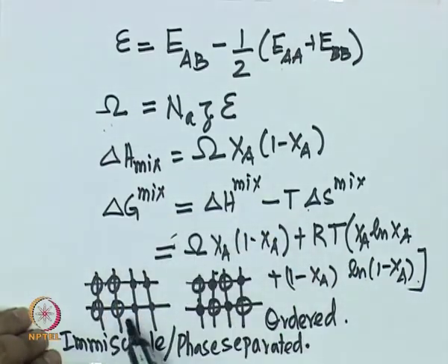the sign of omega decides whether the system is going to phase separate or the system is going to order. The models that we are going to talk about in this course, which are known as phase field models, are basically models meant to study this kind of phase separation by a specific mechanism known as spinodal decomposition, and ordering. Basically, all phase field models can be thought of as models built from these two basic components. Model one, which is known as the Cahn-Hilliard model, was written to explain this phase separation behavior through a specific mechanism, and another model, which is known as the Allen-Cahn model, was written to describe this ordering behavior.